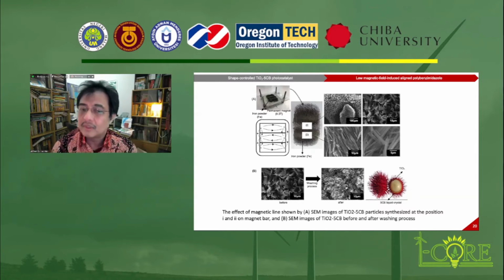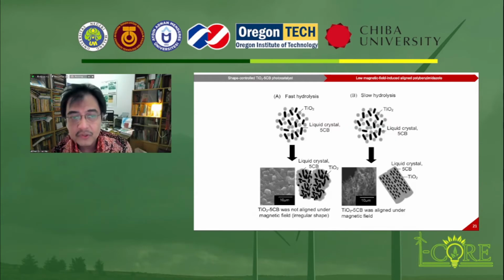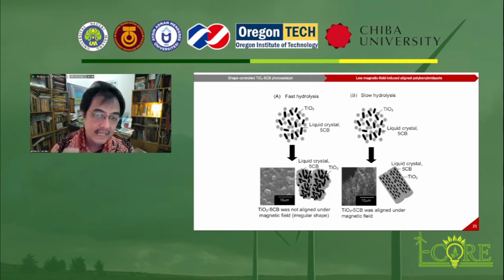Okay, now we need to think about what is the main factor. The main factor contributing to the successful alignment of the material with the magnetic field is the hydrolysis process of the precursor, consisting of the titanium butoxide and a mixture of water and alcohol. We try to control the hydrolysis time to be as long as possible, so that the material has time to align with the magnetic field. If the hydrolysis process is fast, then there is no chance for the material to self-assemble and align with the magnet. In this case, it took about 3 days for the hydrolysis process so that the titania liquid crystals were aligned under magnetic field. So the key for this experiment is the hydrolysis time.